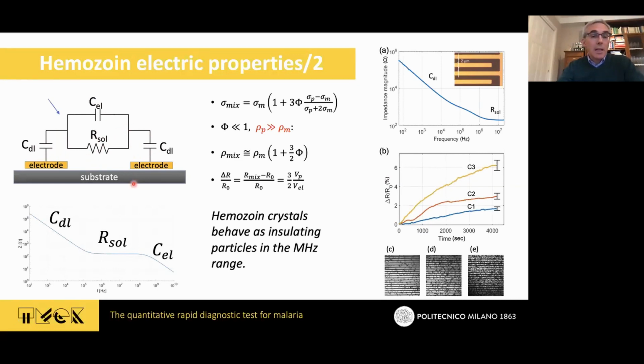Which means that at the end of the day, if you look at the impedance as a function of the frequency in this typical impedimeter detection scheme, you find that there is an initial part which is dominated by the double layer capacitance, and another one dominated by the capacitance of the electrode. But you are interested in this intermediate region in which it's really the solution resistance which plays the major role. And you have to work here at about 1 megahertz or something like that. In this region, you can exploit Maxwell theory for the conductance of a suspension of particles, and you discover that due to the accumulation of some particles between the electrodes in this region, you will observe a percentage change of the resistance that will be proportional to what? To the volume of the particles divided by the probing volume of the electrode.